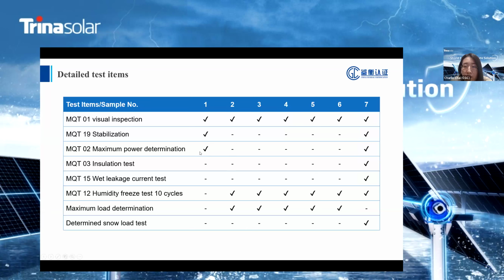As described in previous slides, test sample number 1 is a reference, only going through visual inspection, stabilization, and maximum power determination. Samples number 2 to 6 are used to determine the maximum snow load, which only do visual inspection, humidity freeze, 10 cycles, and maximum load determination. Sample number 7 is used to verify the determined snow load, which requires almost all the tests except for the maximum load determination.